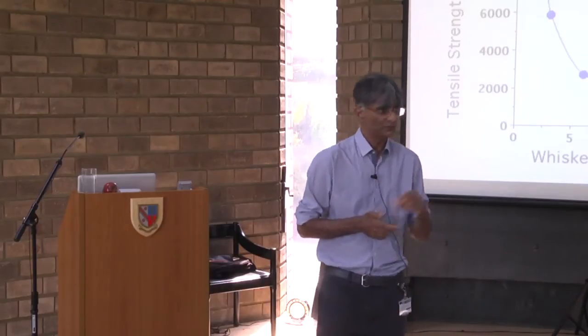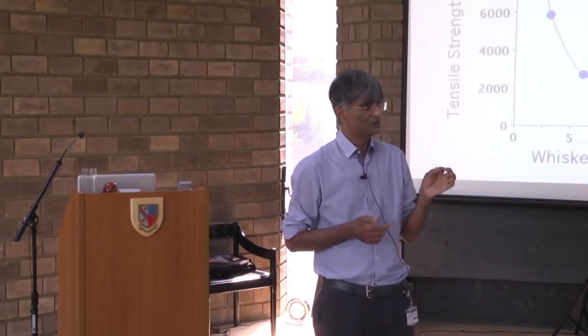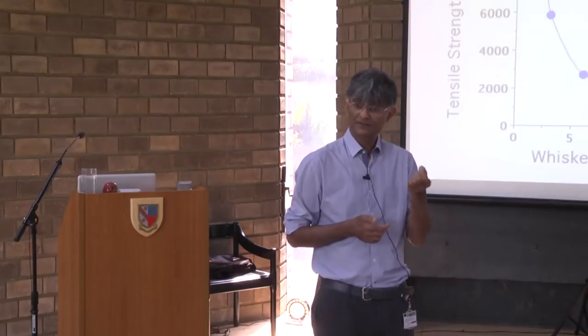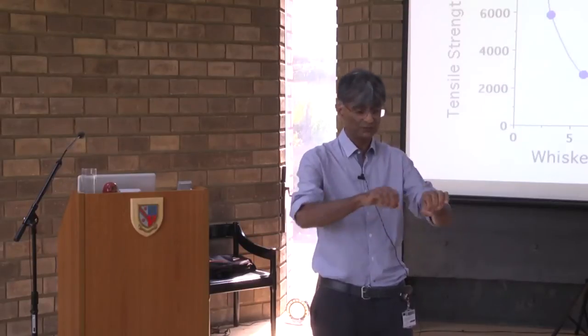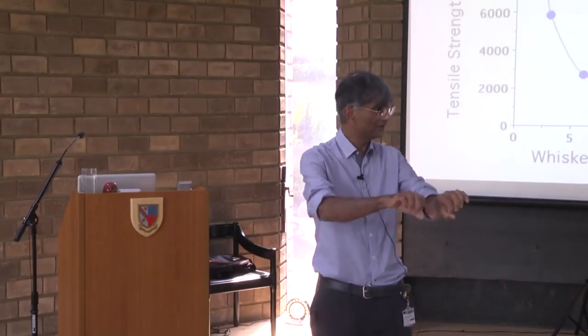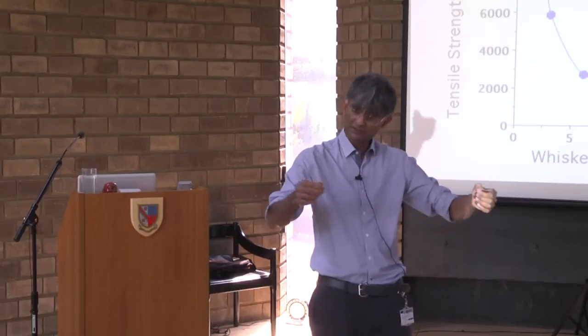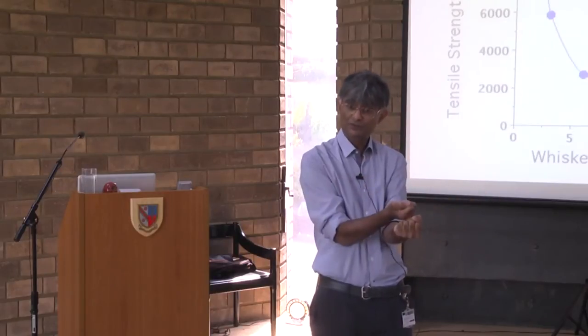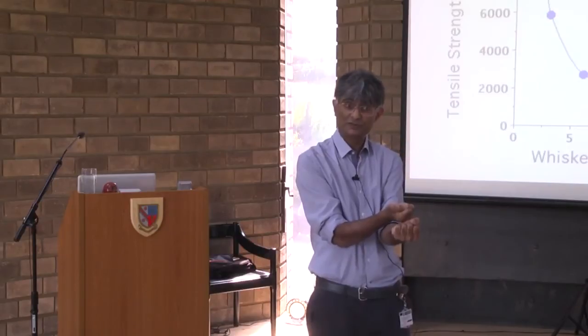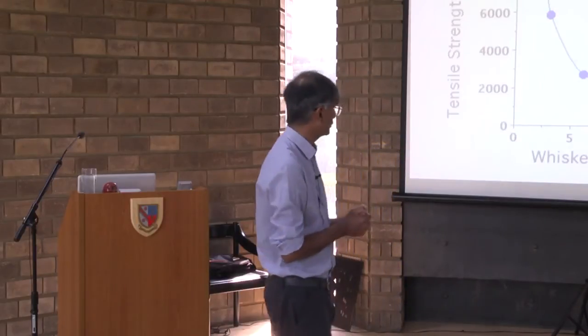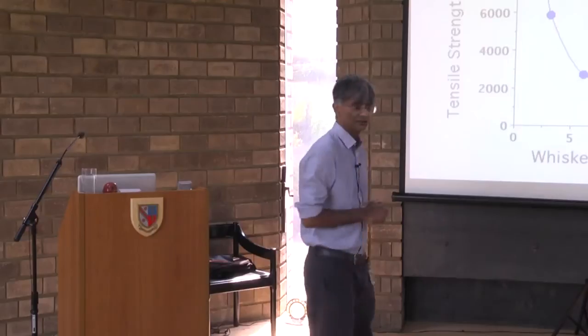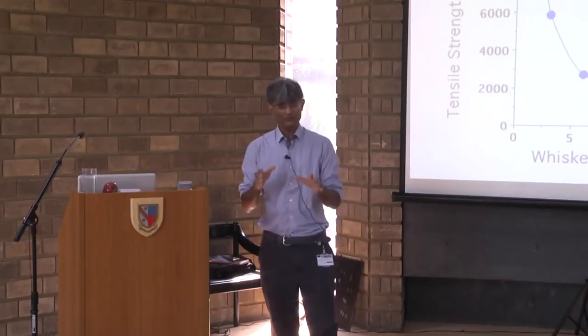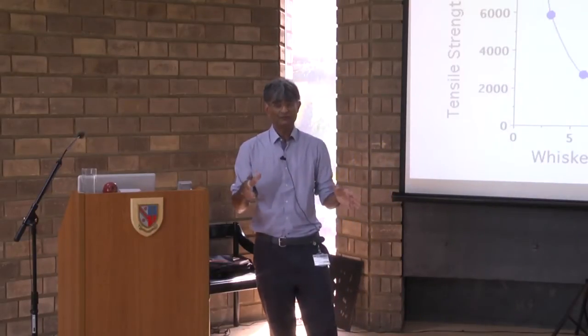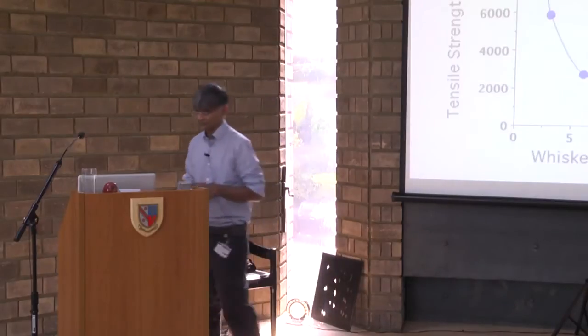And that's because when you make something very small, the chances of getting a defect in there are very, very small. And that's why, if you take a glass rod, you can't bend it, it will shatter. But if you take a glass fiber, you can do that without shattering it, because the chances of finding a defect are much smaller. So we knew this back in 1956, that if you try to make things perfect, then there will be a problem as soon as you scale it up.